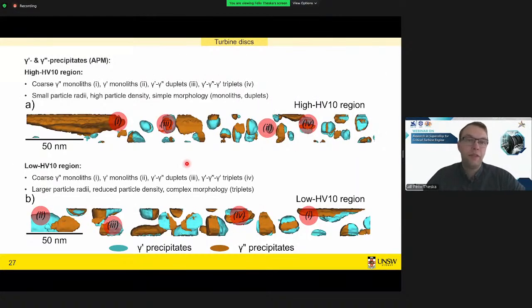And we can take the same material and put it in the atom probe. On the top part, we see the high hardness region. We can apply our toolbox with these methods and find that the particles are overall smaller with a higher density. So that fits very well what we have observed in the TEM, but they also have a simpler morphology. So we find less of these triplets, but more duplets. Whereas in the low hardness region on the bottom, we find larger particles, less densely arranged, and more in a triplet morphology.